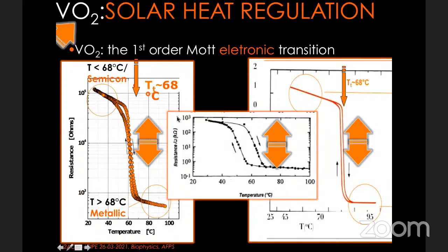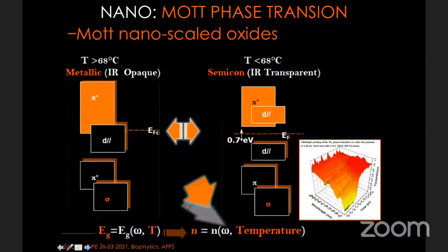As you can see, the resistance of this material versus the temperature has that behavior with the hysteresis. And the hysteresis depends on the quality of the film. Here is a spin-coated film. Here is a thin film made by laser ablation. And here is a bulk crystal. Nonetheless, the one who does this is this very old crystal. It's a Mott-type crystal, VO2. And this VO2 does it.